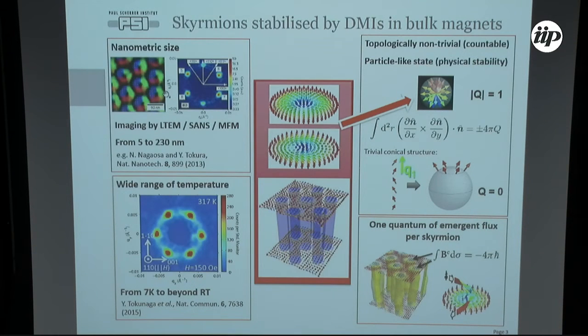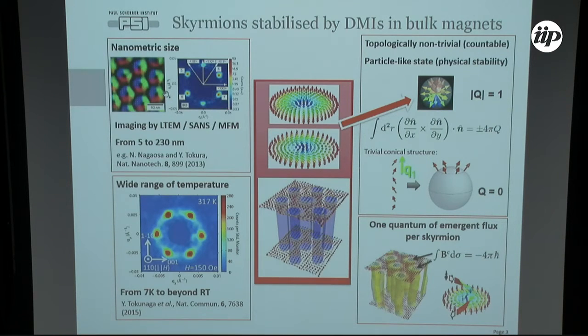This is my introduction to skyrmions. I won't spend much time on this because Charles has already covered it. Skyrmions reported in the literature generally come in two flavors: the Néel-type skyrmion and the chiral Bloch-type skyrmion. These are cross-sections in a plane perpendicular to the applied magnetic field. You can see these are multi-spin objects extending over many unit cells in a lattice. In the third dimension, along the direction of the magnetic field, these structures are translation invariant — this is where we get the picture of vortices.